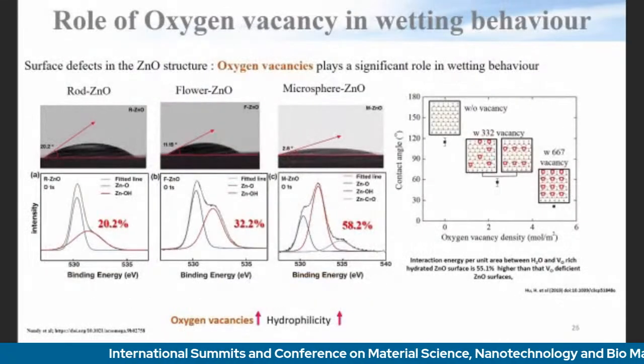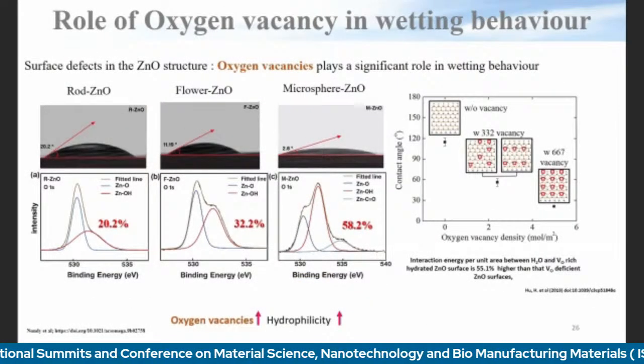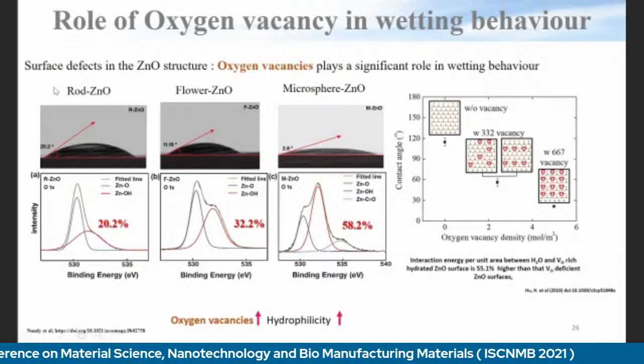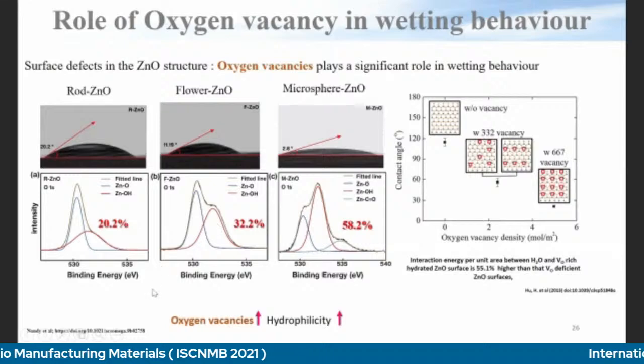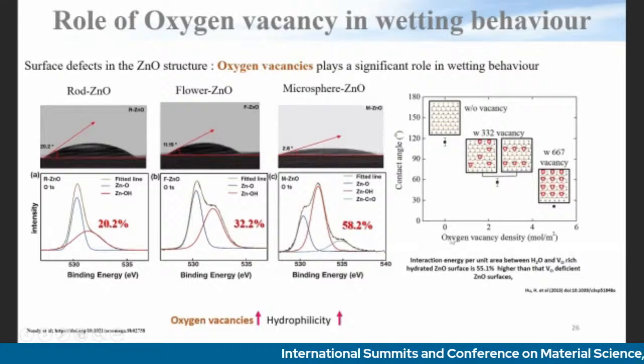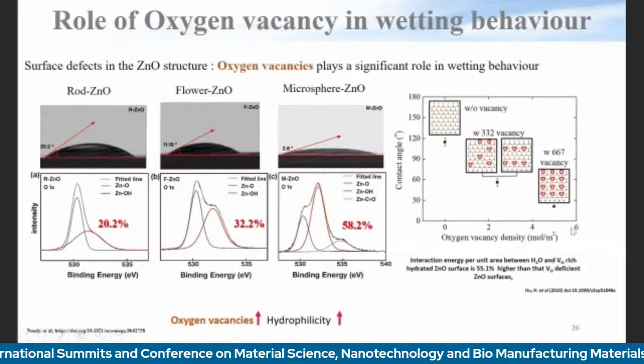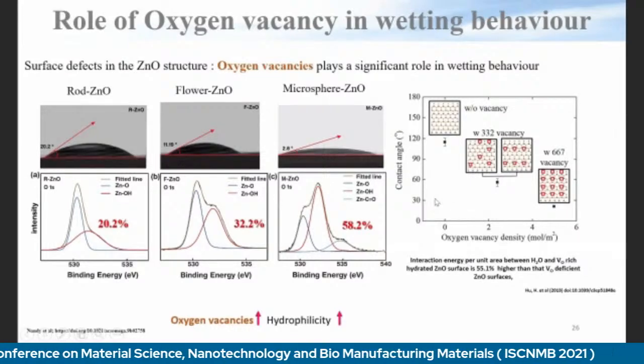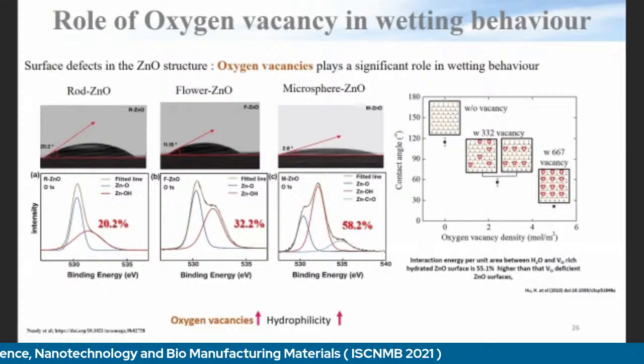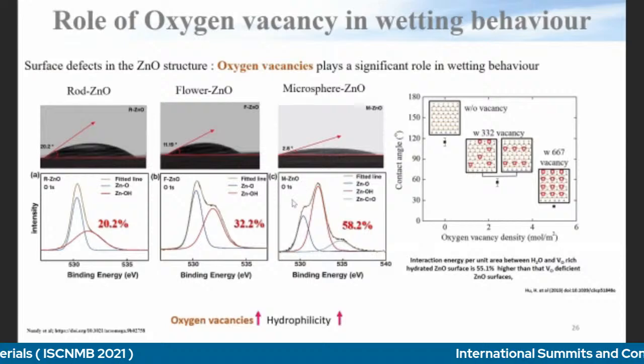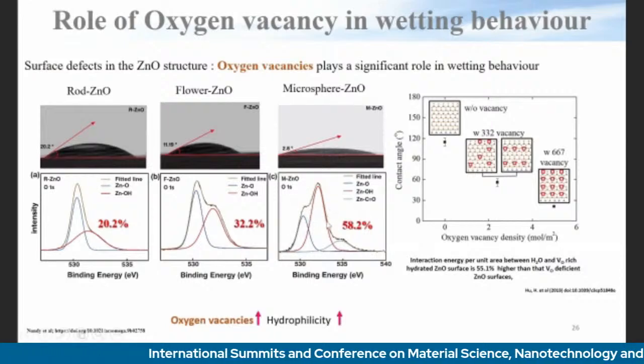Next, we try to explain why we have such a good result, because we know that when we move from rod to flower to microsphere, we have different oxygen vacancies, and we know that enhanced oxygen vacancies create the super hydrophilicity. Previously it was theoretically proved that when the oxygen vacancies improve, your contact angle decreases. That means you have the hydrophilic property, and when you have low oxygen vacancies, you will have a higher contact angle. That means you have the hydrophobic. So theoretically we also found these things, and so we can say that our work went in the right direction.